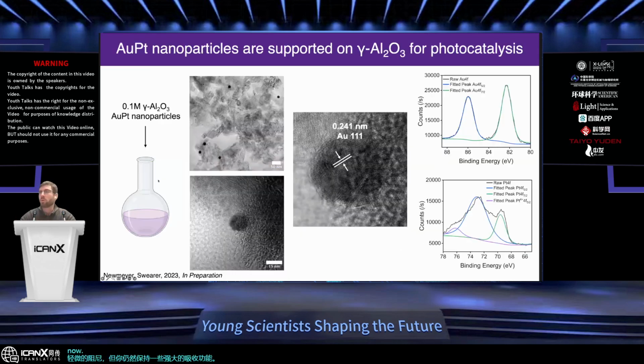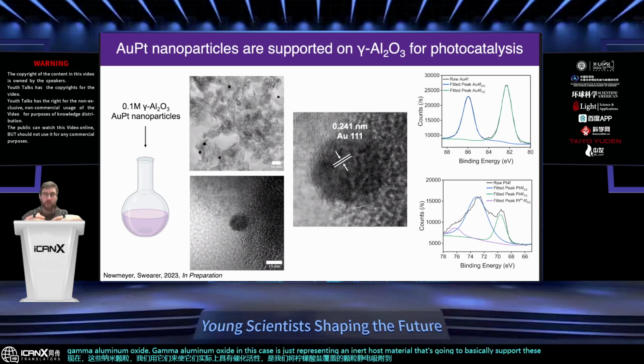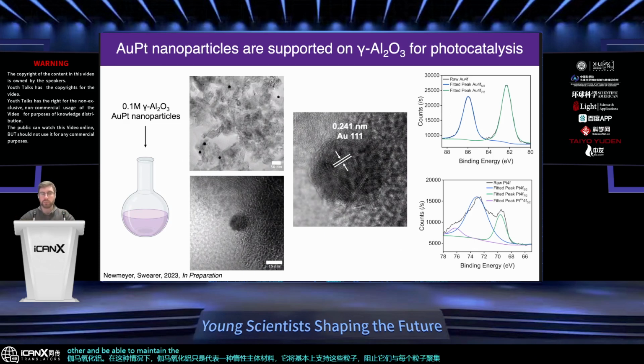Now, to make these nanoparticles catalytically active, we do electrostatic adsorption of the particles that are capped with citrate onto the surface of gamma aluminum oxide. Gamma aluminum oxide in this case is just representing an inert host material that's going to support these particles, stop them from aggregating with each other, and maintain the individual resonances that we are interested in.